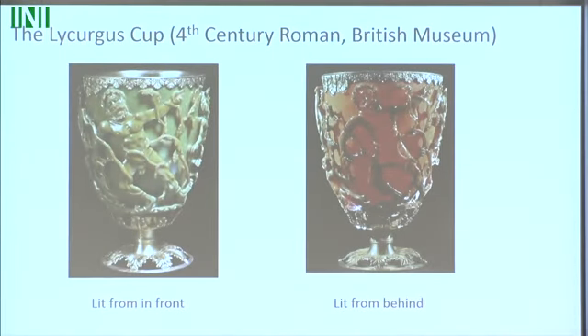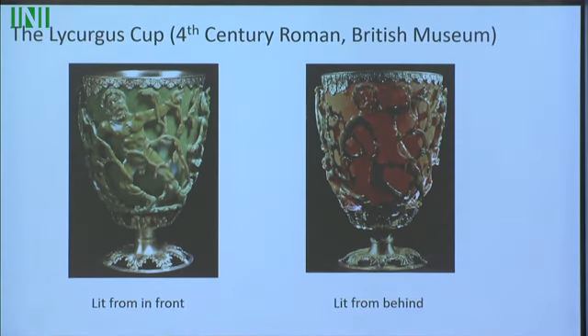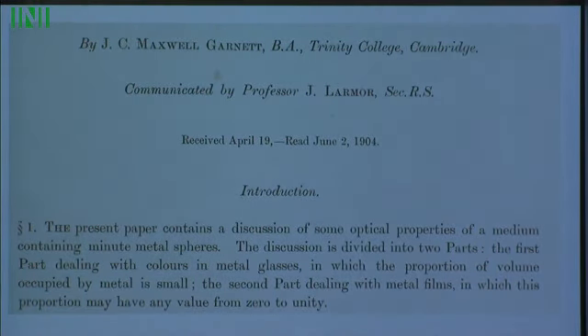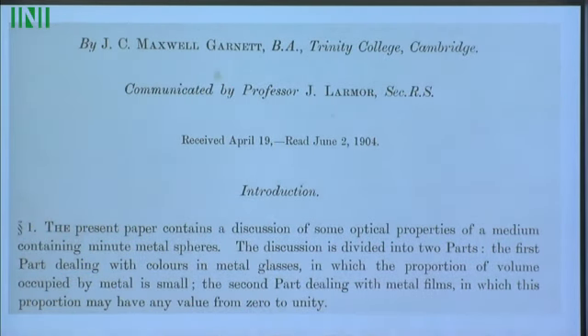Another old example comes from the British Museum. If you haven't seen it before, this is the Lycurgus Cup. What's striking is that the glass in the cup takes completely different colors depending upon whether the light source is in front or behind. That's due to the small metal particles inside the glass, nano-sized particles of silver and gold. The theory for that is the same as for stained glass windows in old churches, to get the beautiful reds. It's a composite of gold spheres and glass. It's not a chemical reaction at all, but rather a resonance caused by the interaction of electric fields with spheres.